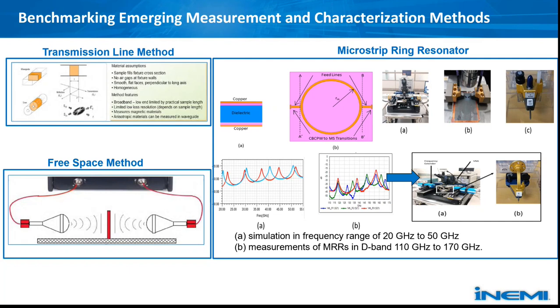The other methods which we considered were free space methods, like the one shown on the slide, in which we are using 2 antennas with the sample between them. We are performing a measurement of the transmission coefficient and also the reflection coefficient. With this method, we can go beyond 100 gigahertz with our characterization of materials. The third one is the microstrip ring resonator. What you can see on the slide are examples of this kind of device operating in the D band, so between 110 and up to 170 gigahertz. So those are our listed candidates for higher frequency material characterization.